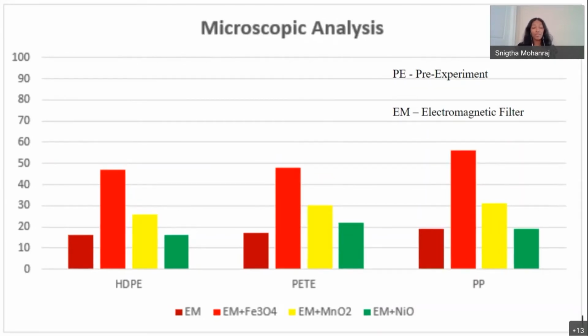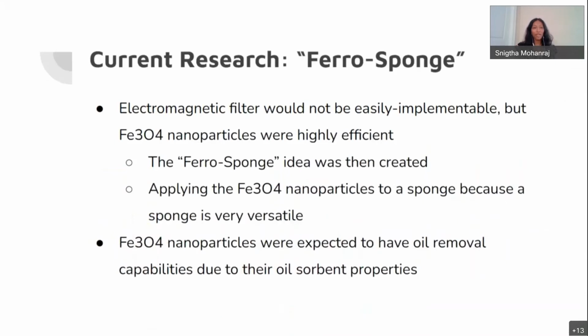And this was again proven in the microscopic analysis, where the electromagnetic filter with iron oxide removed the most amount of microplastics in contaminated samples. But I realized that the electromagnetic filter wouldn't really be easily implementable, especially on mass scales. But it was proven that the iron oxide nanoparticles were highly efficient. So I wanted to further develop this, and then the ferrosponge idea was born.